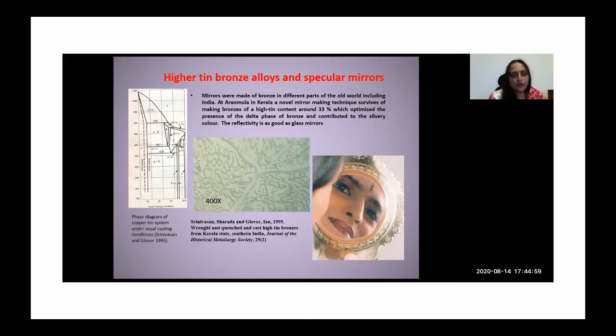So I've brought you back to this phase diagram, the copper-tin system. So if you look at what happens around 33 or so percent tin, one thing you have to realize is that many of these phase diagrams were made for equilibrium conditions, which is only laboratory conditions. But this is one of those which has been attempted under usual or normal casting conditions. And there you see that the delta phase actually gets retained pretty much at room temperature. And that's what's happening in these mirrors.